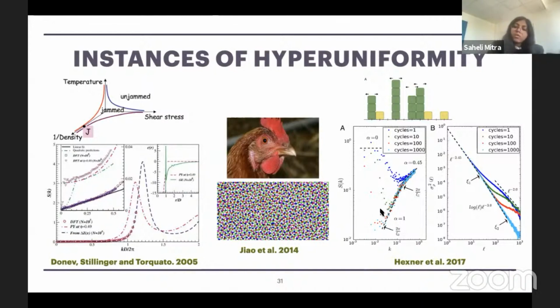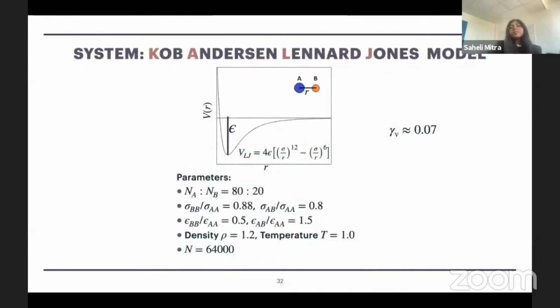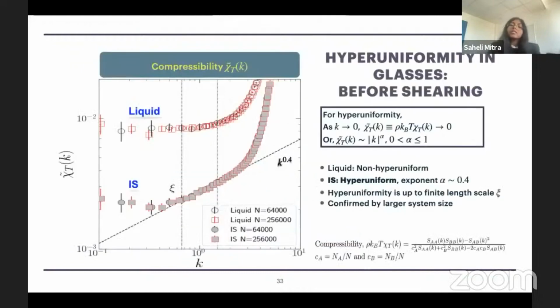For that, we start with the model glass former, which is a 50-50 binary mixture of particles interacting through Lennard-Jones potential. We work at high density 1.2 and high temperature. For this system, the yielding amplitude is 0.07. First, we look into the system and what happens even before shearing. So we compute the wave vector dependent compressibility instead of the structure factor.